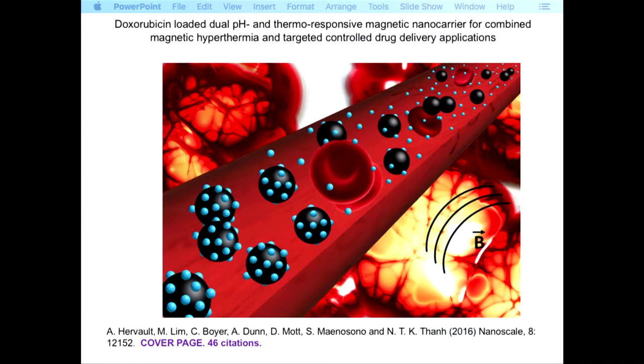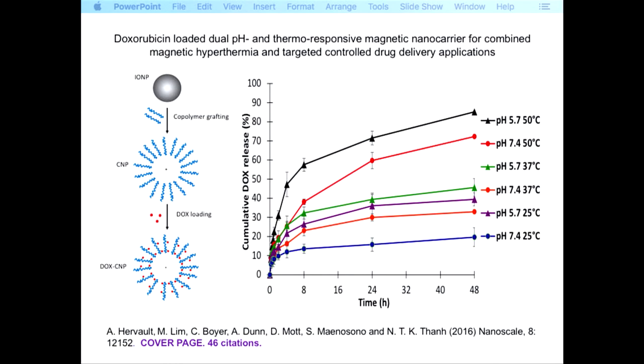You remove all the hot organic solvent and put in water, then the particles are dispersed in the water. Then what we want to do is encapsulate the drug inside the magnetic nanoparticle. Remember the slide I showed you with the European Investment Bank, they invested in MagForce, but in combination with chemotherapy. So we want to combine the chemotherapy here: when you heat the magnetic nanoparticle, the polymer will also heat and release the drug. And then here we design the system so that it is also sensitive to pH, because in the cancer cell it's more acidic. As I show you two curves, the first curve at the higher pH 7.4 and lower temperature 25, the drug release is not so high, but in the black curve on top, in the acidic environment and also at high temperature, you get more drug release.